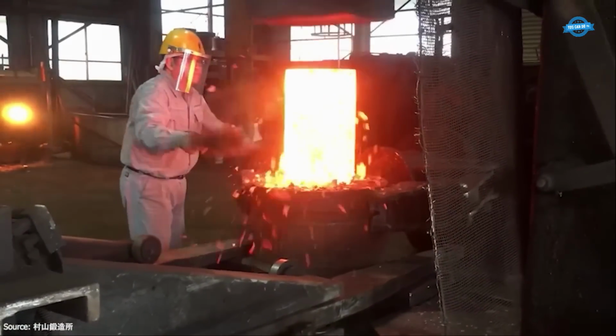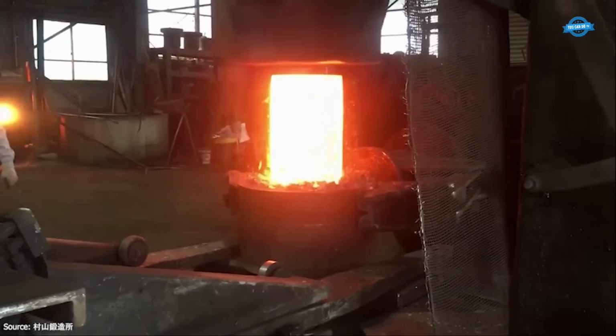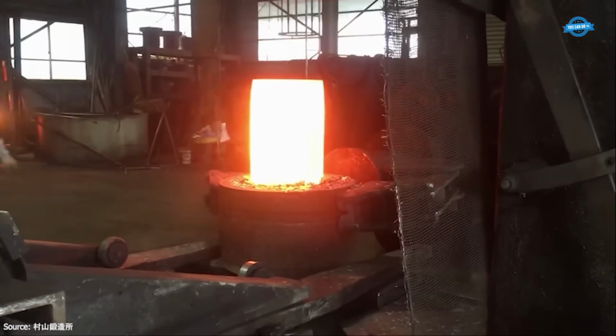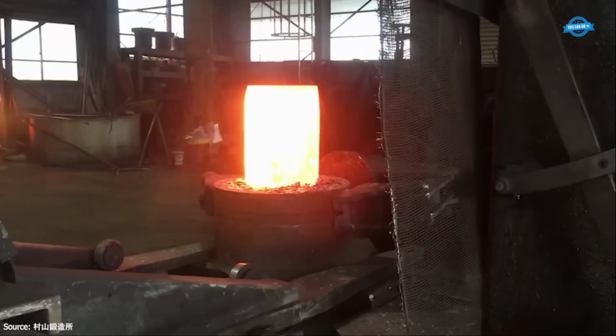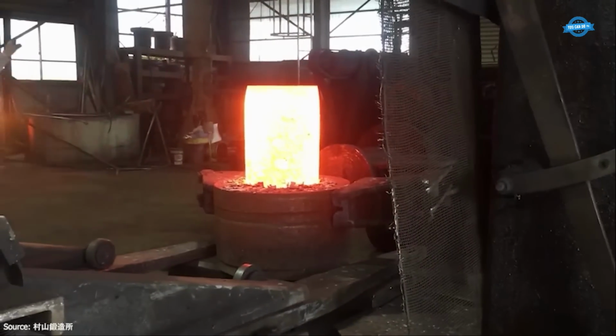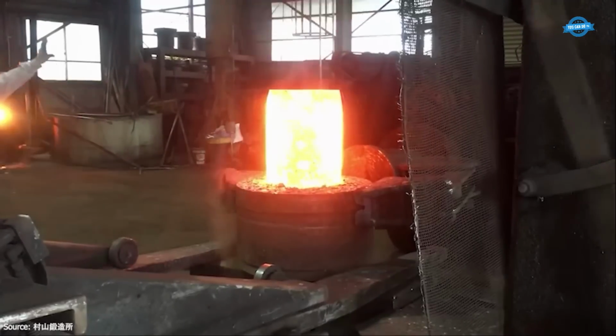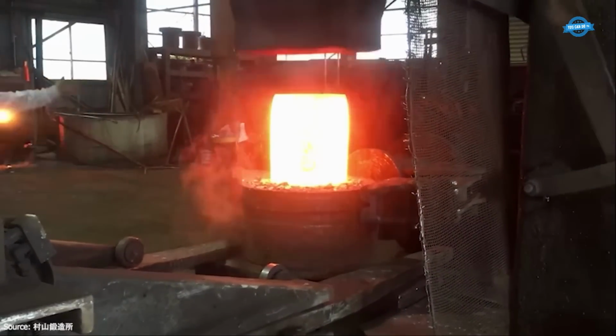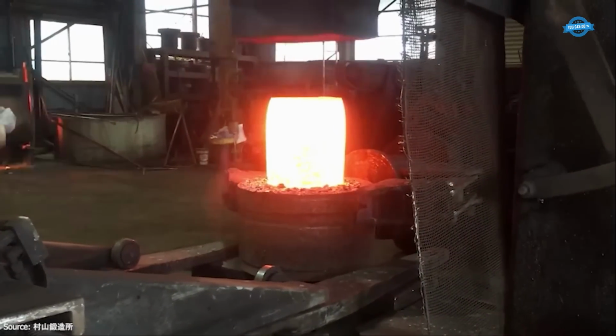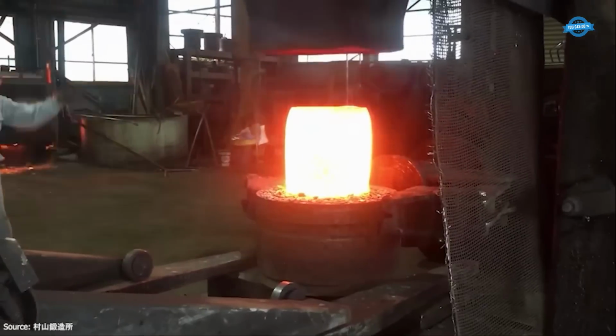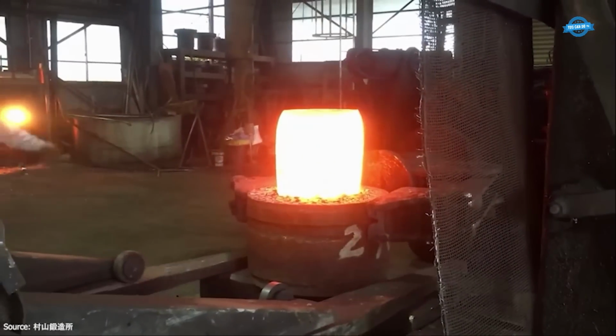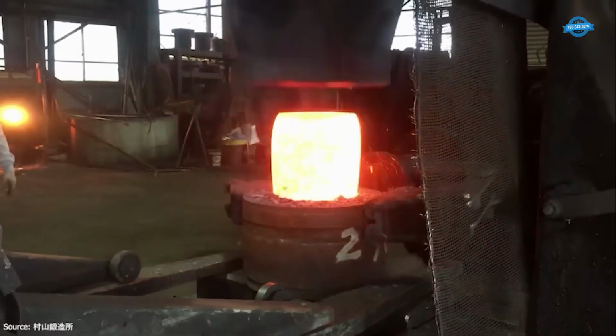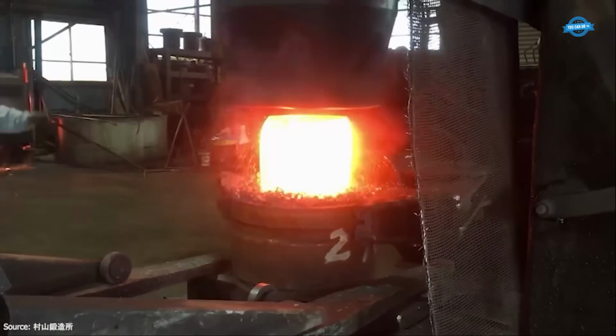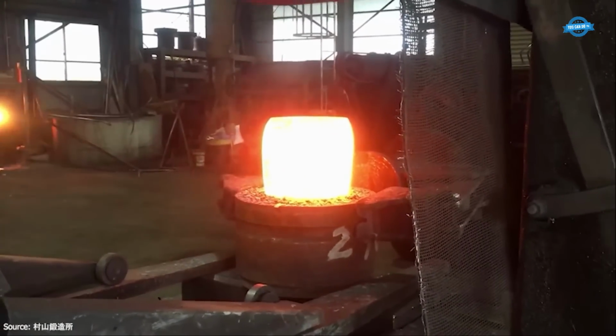The billets are heated uniformly in a gas-fired furnace to a forging temperature of around 1,200 degrees Celsius. This high temperature is necessary to soften the steel sufficiently for deformation while maintaining its structural integrity. Uniform heating ensures that the internal temperature of the billet matches the surface, minimizing internal stresses and potential defects during forging. The billet is removed from the furnace.